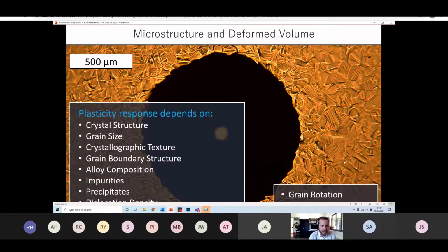So you can see from that micrograph that our indents are comparatively large, at least when compared to those produced by, for example, nano indentation, or even maybe those produced by a normal Vickers hardness test. And this is deliberate. We deliberately indent materials on a fairly large or coarse scale. They're still quite small, don't forget. That indent on the screen right now is only about a millimetre in diameter. So it's still comparatively small. It's just bigger than things like nano indentation.